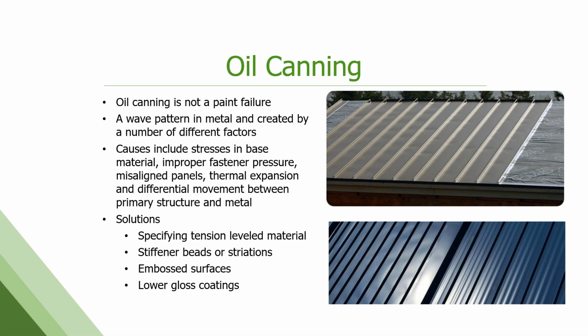It can be due to stresses in the base material, improper fastener pressure, misaligned panels, thermal expansion that wasn't accounted for. But there are ways to combat it, and that is specifying tension leveled material, which is pretty standard for all coil producers. You can use stiffener beads or striations in a panel design, and that's the example on the bottom. This is the exact same profile of panel with and without striations, and you can see the difference in the buckling. Embossed surfaces help break this phenomenon up, and with lower gloss coatings, while the oil canning is still there, you don't see it as readily.